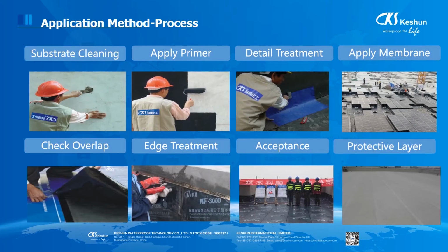Here you can see the method process. First, we do substrate cleaning and apply primer, and then we do detail treatment. After that, we apply large area membranes, and we check the overlap bonding, and we do edge treatment. The final step is acceptance and making the protective layer. Basically, APF-3000 is similar to torch membrane. The difference between these two membranes is that we don't need to use torch with APF-3000, and also this membrane can use 3 different kinds of primer.